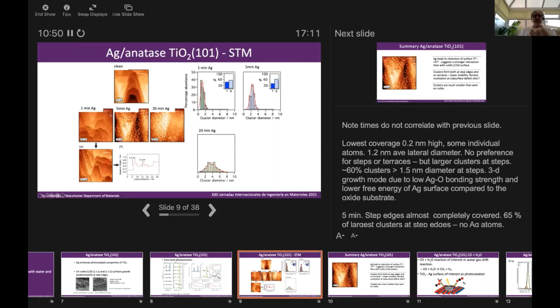So here we looked at some STM of this surface. This is the clean surface, with those triangular structures that you see on this anatase 101 surface. And we found when we deposit 1 minute of silver, the timing, I should point out, is not comparable to the previous slide. In the previous slide, the source and the sample were a long way apart, so we had to evaporate for much longer to get similar coverages. So we believe this coverage here is similar to what we achieved after 20 minutes for the spectra we showed on the previous slide. So we're calling this the 1 monolayer coverage.